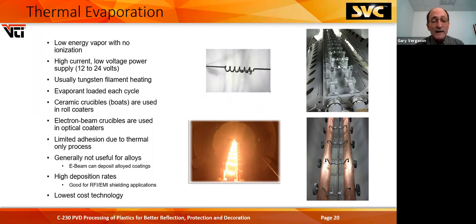The parts need to be really clean, and it has, I'm saying limited adhesion, because it's only a thermal process. You don't have any ions, so you don't get any ion motion, any movement on the substrate and release of that energy. It's just totally thermal. Generally, it's not useful for doing alloys, although E-beam can deposit in all sorts of alloy coatings. High deposition rate. It's good for RFI EMI shielding applications if you're doing aluminum, because you put a lot of aluminum down fast, and it's the lowest cost technology.